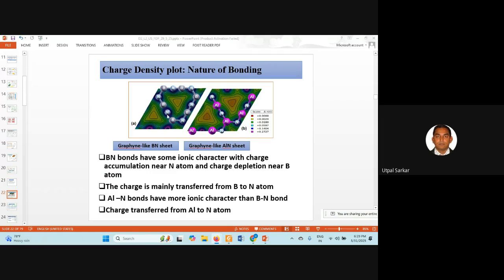You see here, these are not purely covalent bonds. Electrons are localized around the nitrogen atoms, and electrons are depleted in the boron. So these are a little bit polar types of bonds, and ionic character is present. BN bonds have some ionic character with charge accumulation near the nitrogen atom and charge depletion near the boron atom, and charge is mainly transferred from boron to nitrogen, or aluminum to nitrogen. And the aluminum nitrogen bond is more ionic.